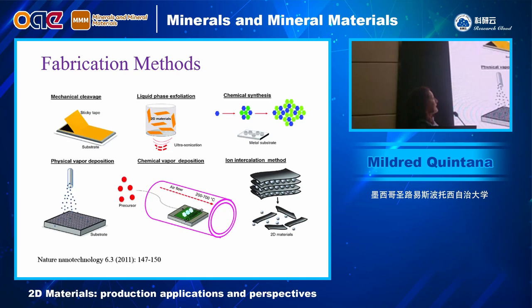There are other physical methodologies that are very expensive because you need ultra high vacuum and a lot of energy to produce graphene from carbon atoms. And the technique that is most used now for electronic applications is CVD, chemical vapor deposition synthesis, where you have a quartz tube and you put a flux of gas and the precursors, and you heat this in an oven, and then you start the growing on a catalyst surface. This is very used for all the electronic applications. If you want to do transistors or chips, then you work with the CVD.